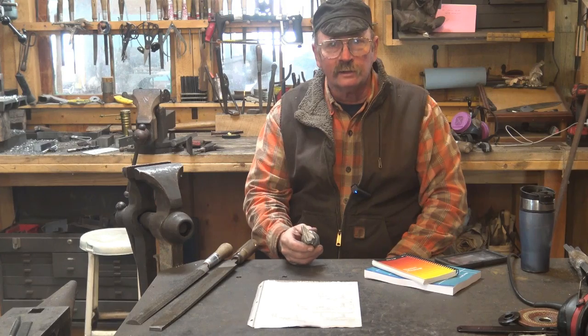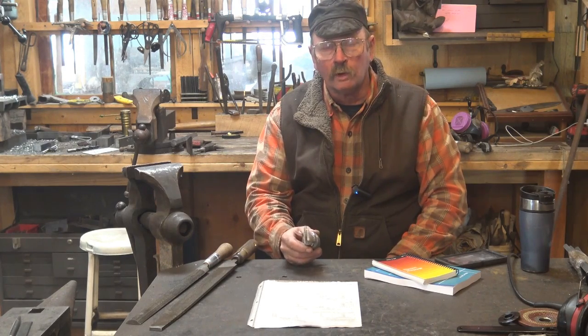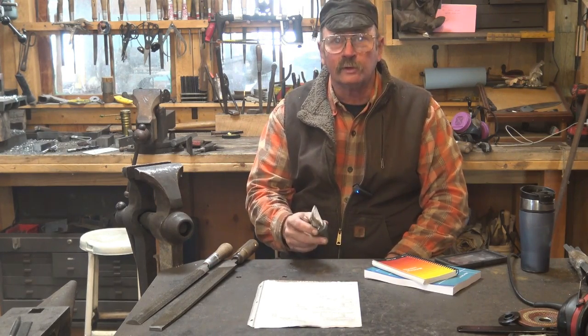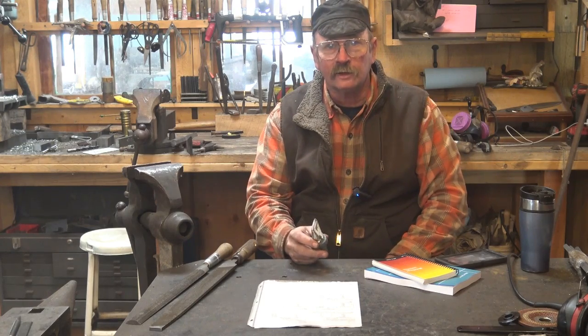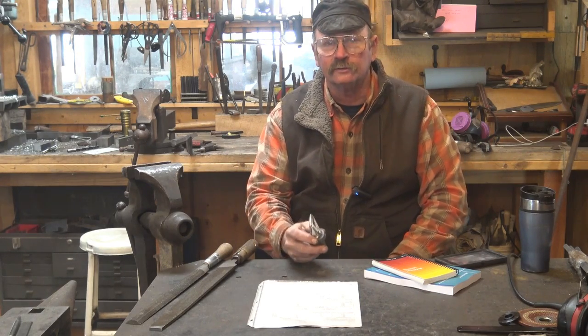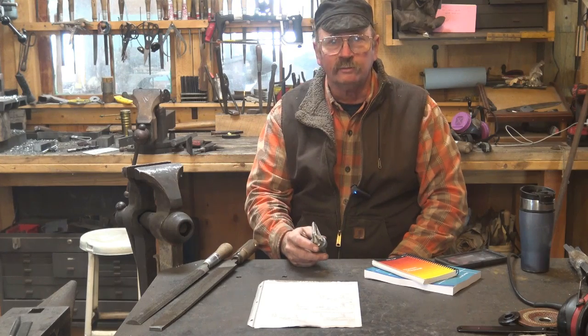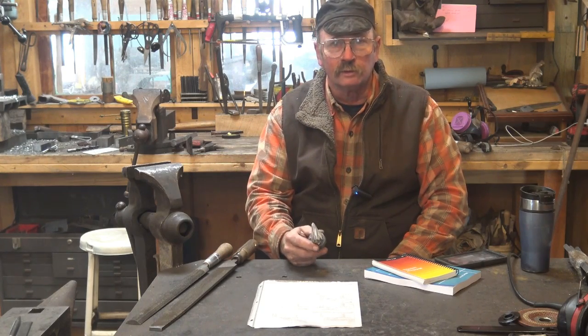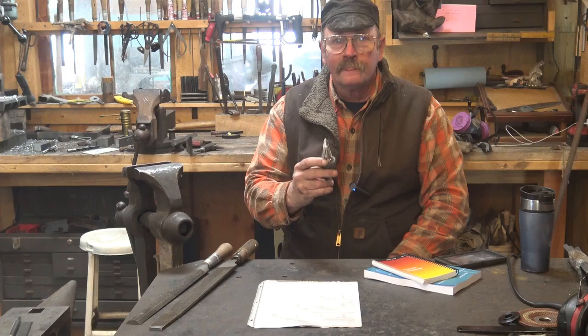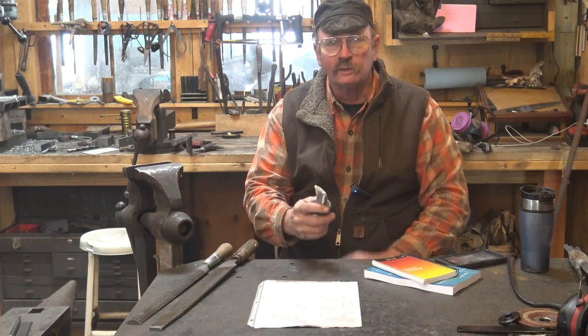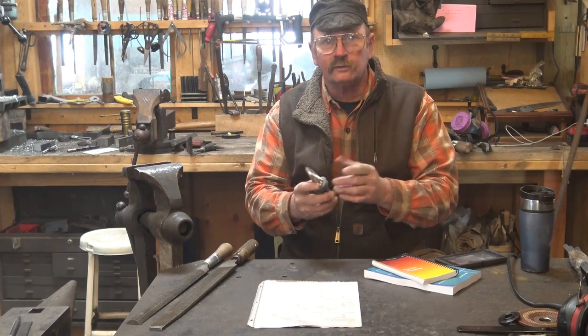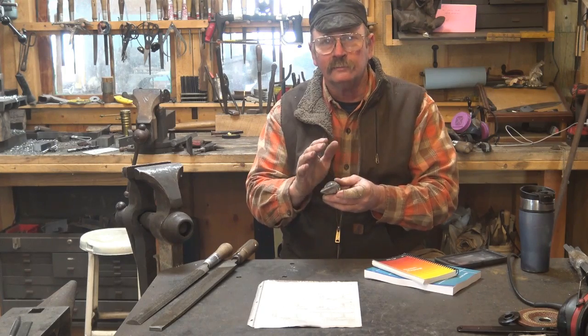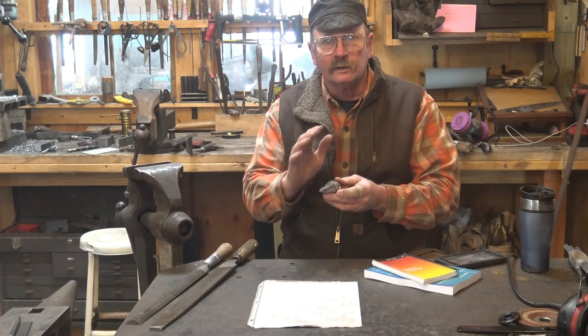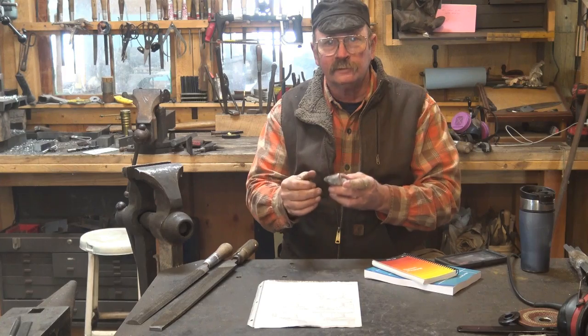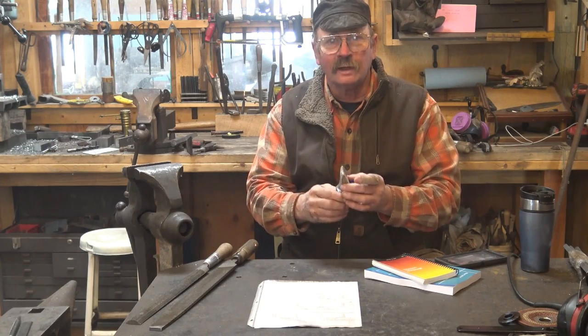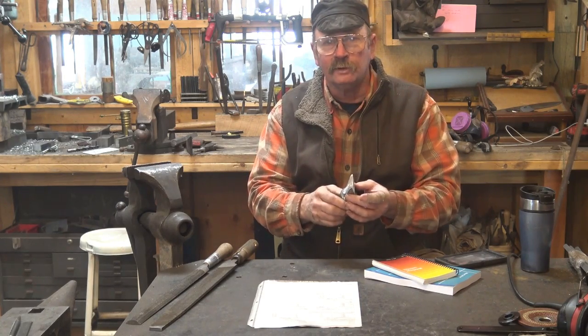So after it's been annealed and/or normalized, or maybe you've done both for some reason. Some people will run it through an annealing cycle and then several normalizing cycles. And that's popular with knife makers, but we're not talking knives here, we're talking chisels. The next step, that's when you do all your grinding. You're not going to hurt the heat treat because it hasn't been hardened and tempered. So you can grind it, you don't have to worry if it gets hot. Get it to shape. Then it's time to harden and temper.